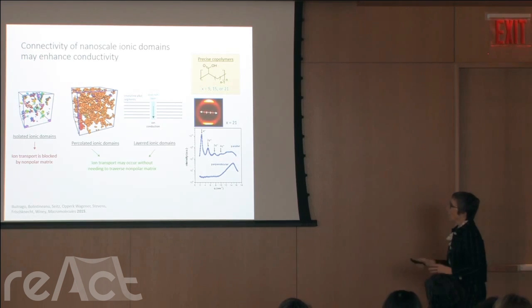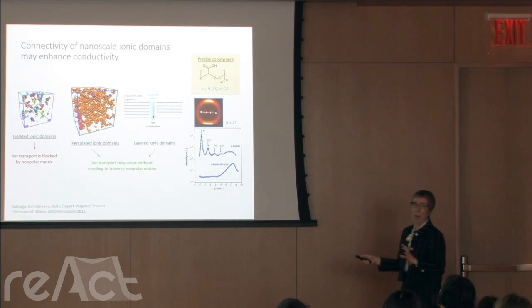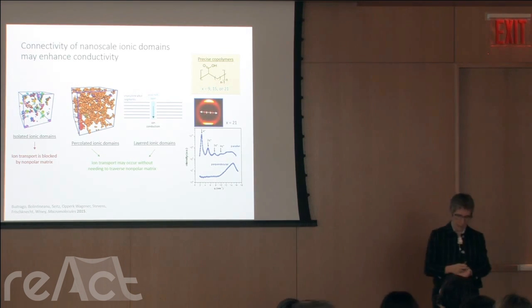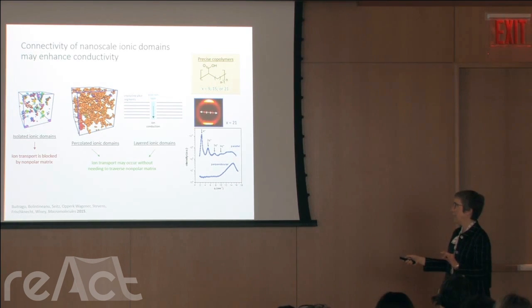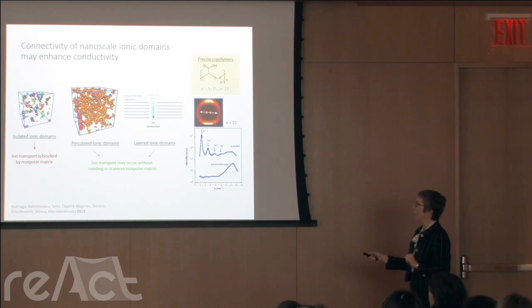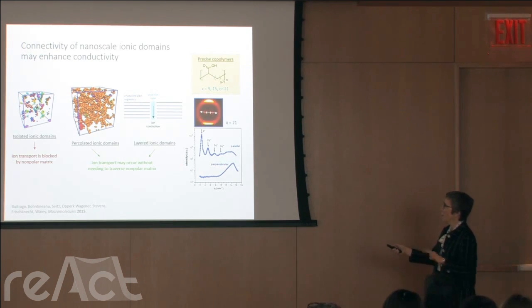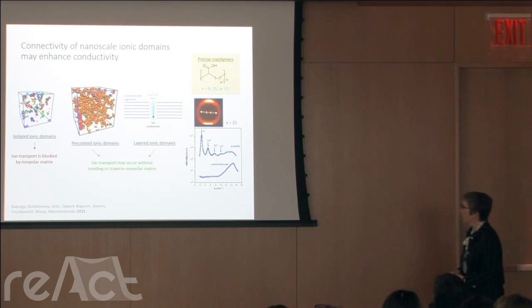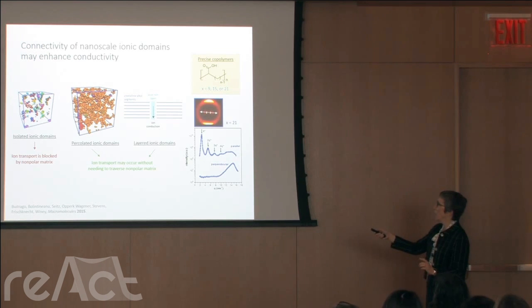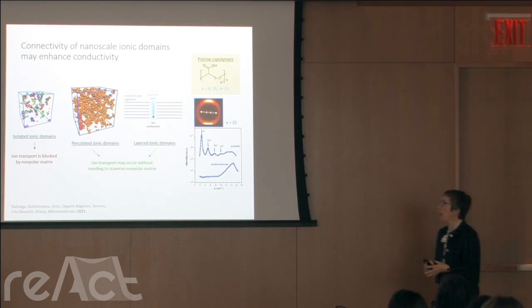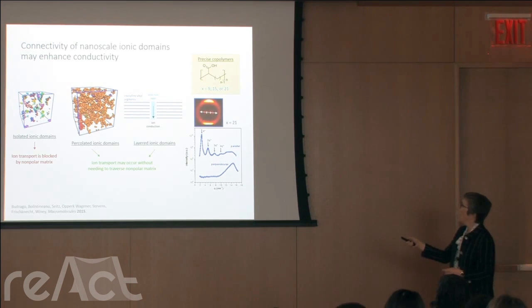The most typical morphology in single ion conductors is discrete aggregates. These are atomistic molecular dynamics simulations, where the only thing that you're seeing is the charged entity, and the polymer chain is invisible in the rendering of the simulation results. So in this case, we have discrete isolated aggregates. This is not going to work so well for ion transport. But in this case, the whole golden, orangey color is one big aggregate. It is stringy, it is branched, and it's percolated the entire simulation box. This is a 6.5 nanometer simulation box. So this would be good as a percolated structure. You could imagine introducing a lithium at the top, and it could shuffle its way down inside these aggregates that are high dielectric constant.